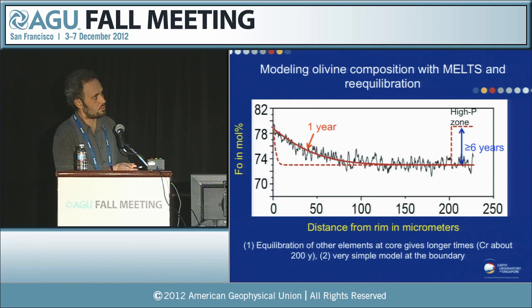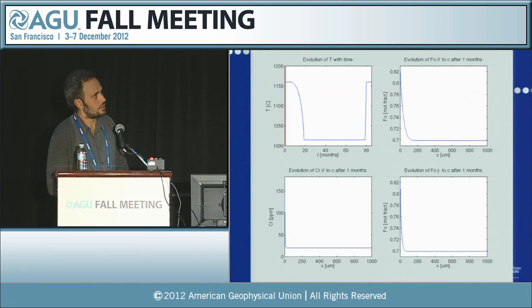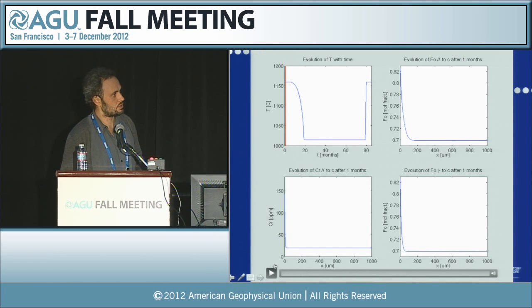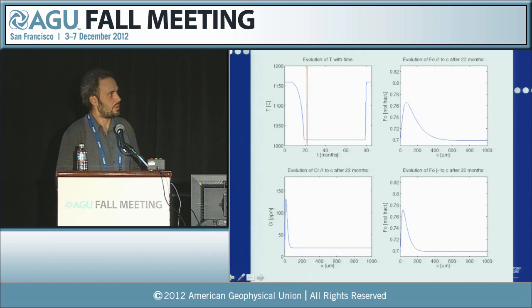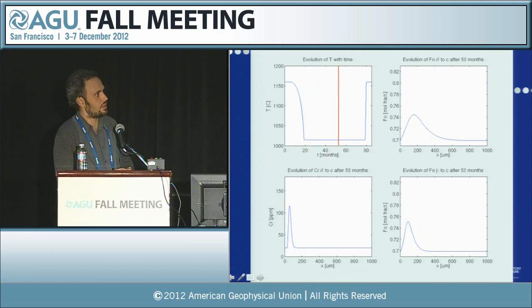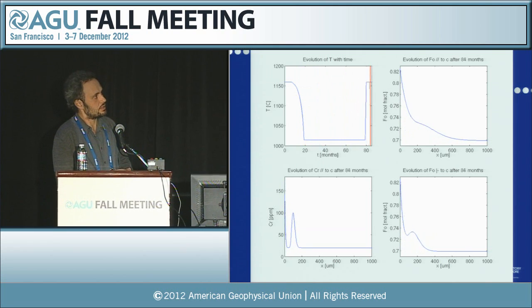There's basically 2 slopes here. So we've done a relatively more sophisticated calculation. There's a little bit of animation here where we simulate 2 replenishments. There's first 1 replenishment here, then constant temperature, another replenishment, and we check how the concentrations change at the boundary. And so basically, you're moving the temperature here, and then the Forsterite is going, and then when the thing kicks up, this goes back up again.